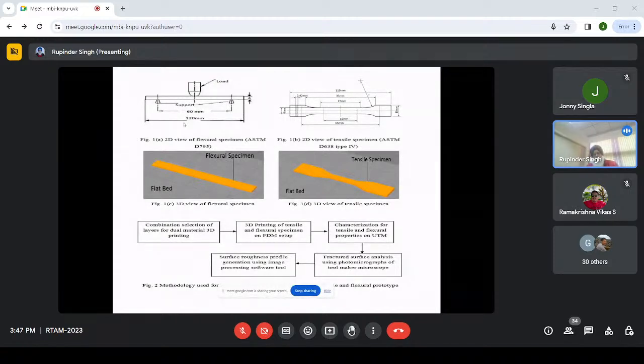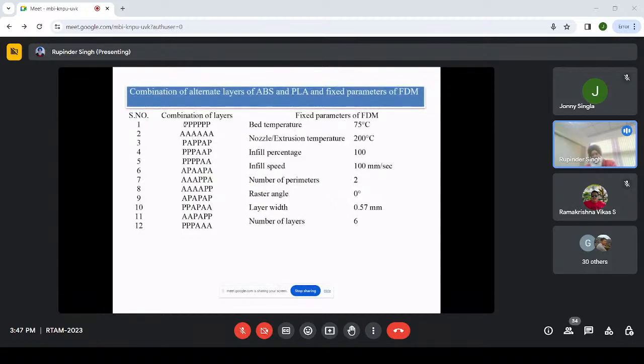Now you can see in this case, this is a flexural loading condition and the tensile loading condition. The coupons were printed, and we use in this case, to have a proof of concept, 2 different materials. One was ABS, another was PLA. We used some fixed parameters like bed temperature was fixed, nozzle temperature was fixed, infill percentage was fixed, infill speed was fixed, number of perimeters, meaning outer layers, 2 perimeters were fixed, raster angle was fixed, layer width, number of layers were fixed as 6.